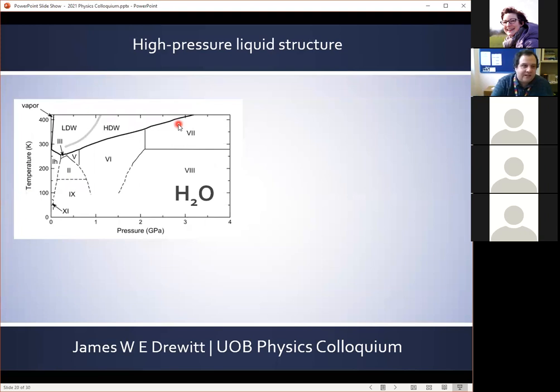This behavior coincides with unusual behavior in the melting curve. So, for example, this is the phase diagram for water, and we see a negative slope in the melting curve with increasing pressure until it becomes positive again, and this coincides with the transformation from low density to high density phases of water.